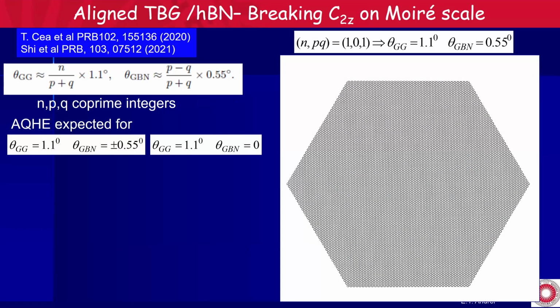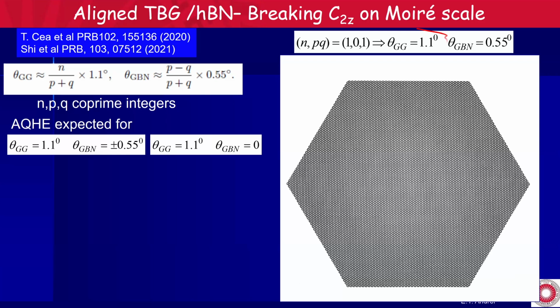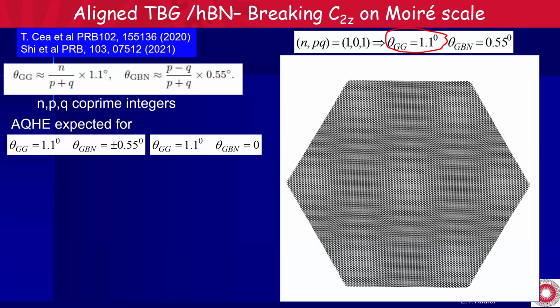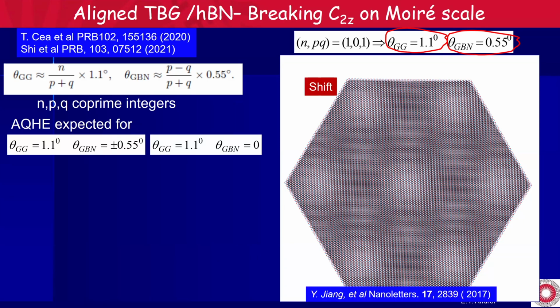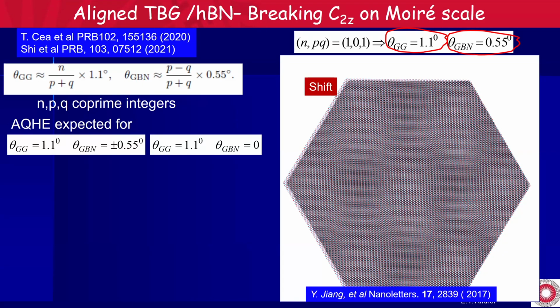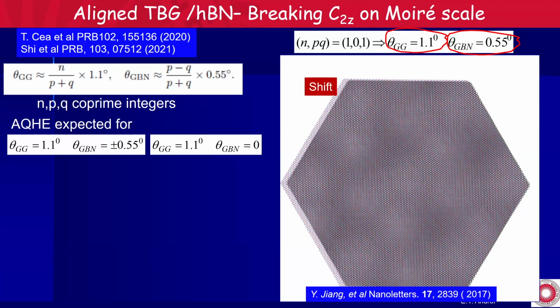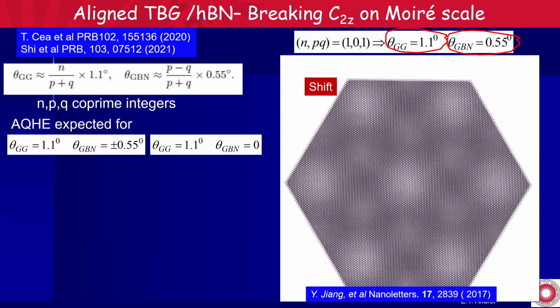Okay, here's my first layer of graphene. I'm bringing on top of it the second layer of graphene. I'm twisting it by 1.1 degrees. I think the moire pattern shows up. And now I'm bringing in the boron nitride on top at 0.55 degrees, and I'm twisting it. Okay, so this is my super moire with the two moires. And now, as an experimentalist, I cannot precisely align, so let's say that I have a little shift. Okay, look what happens. You see, when I shifted by one atomic size, the whole pattern changes, unlike twisted bilayer graphene. This is very challenging experimentally.